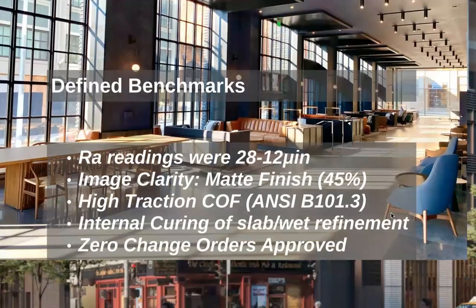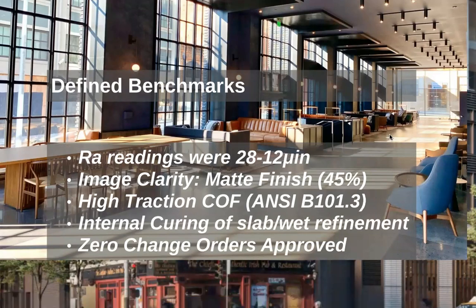You don't have to use these exact micro inch benchmarks, but for a basic polished concrete, your minimum should be somewhere around 30 micro inches. I always do a plus or minus five or six, because I don't want to nail subcontractors to the wall — they need flexibility — but they also need to be sort of around the mark, still delivering pretty close to target.